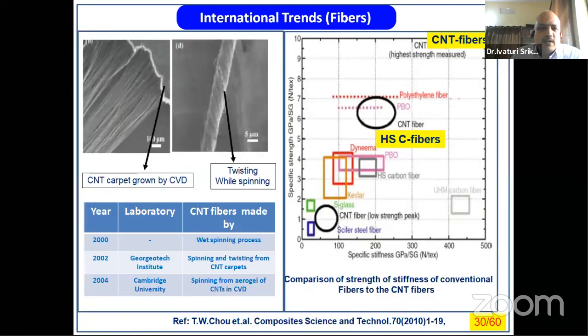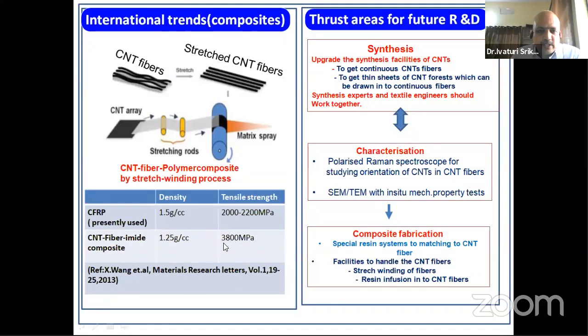So if you see the global trends, what people are doing is they are trying to avoid the carbon fibers completely. They are trying to make continuous CNT fibers. You can see this is a web of CNTs collected in a CVD synthesizer process. From this, continuous CNT fibers are drawn, twisted, and the strength of CNT fibers is around 10 GPa, against around 4 to 6 GPa strength of carbon fibers that we generally use. By using these CNT fibers, people have reported strength of the order of around 4,000 MPa against around 2,000 MPa strength that we generally get with carbon fiber.